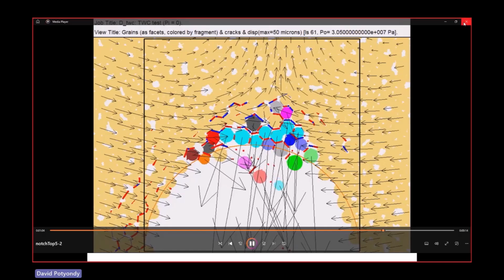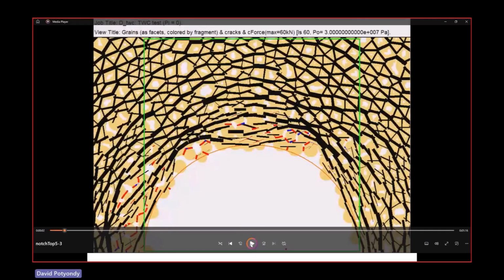Now let's look at the same system, but let's look at the force chains. This is the initial system, and because there is some of this damage here, this material is a little bit less stiff, so you're beginning to see some arching. Thickness is proportional to the magnitude of these force chains. As those cracks happen, this material softens and redirects the stresses up into the rock, producing a big region of compression. And as we all know, the more confinement you have on a rock, the stronger it gets. That's why these breakouts are stable.